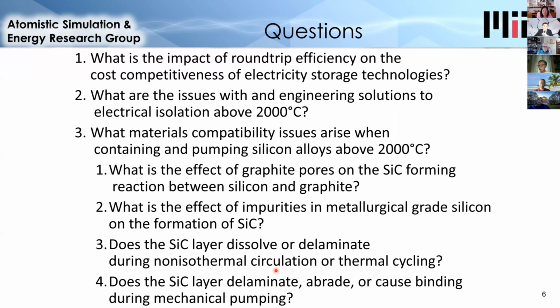What this means is when I'm pumping silicon from the cold tank to the hot tank, so there's a temperature difference and the silicon's moving between it, does that cause a problem, or just thermal cycling by itself, just heating and cooling the heater system, cause problems? And the last question is related to pumping and whether pumping or the act of a dynamic component causes the silicon carbide layer to delaminate, abrade, or cause the pump to bind and stop rotating.